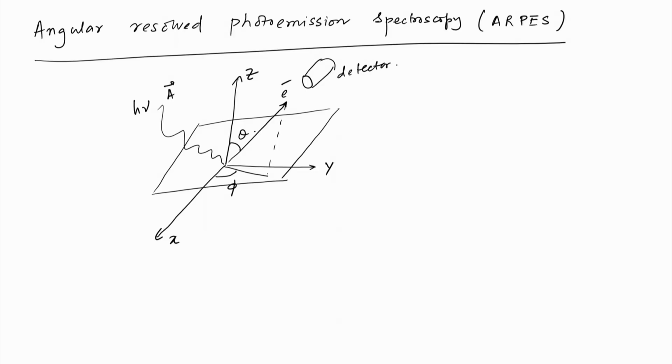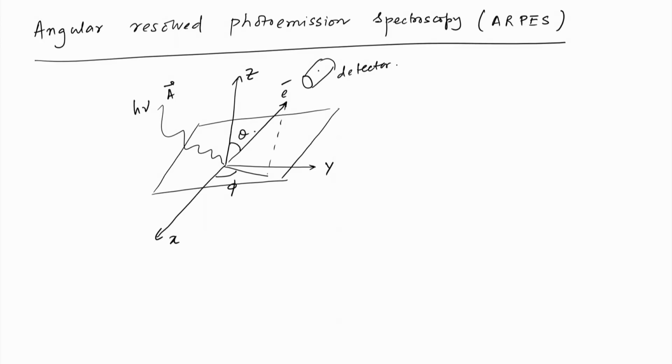So, the photon falls on a certain material which is a superconductor, and then electrons are emitted and collected by the detector. It is very clear that if you have electrons available in certain directions, then only the detector will be able to detect electrons, and this detector can be placed at any angle, covering the full 360 degrees. So, this detector only detects electrons at say 4 points in the kx ky direction, in which the superconductor has gapless points.